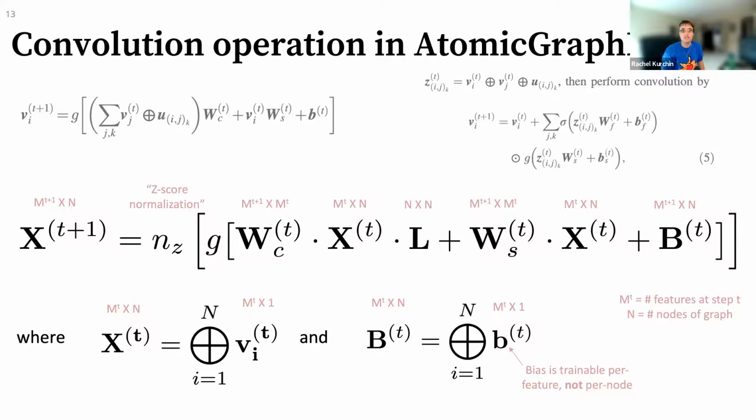What the edge features typically look like, at least in the cgcnn.py, is in fact just a Gaussian basis expansion of the distance between the nodes. So really the only piece of information there is the length of the bond, if you will. There are very sensible physics and materials science oriented reasons to think that that's a useful thing to do. If you imagine surrogatizing electronic interactions that take place at different distances between atoms, you're capturing perhaps in some way different orbitals. So it's very envisionable that those things could be important.